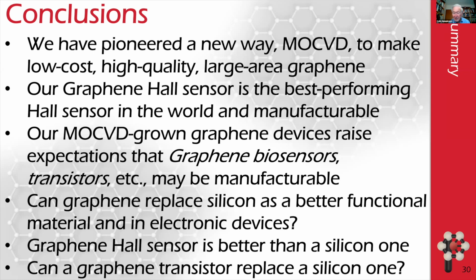It means it changes its sensitivity. And also, quite remarkably, phonons in the substrate affect the mobility of carriers in the graphene. We found out lots of these things, and some of them were known beforehand and sort of not published, but it's really not easy to use. So we've got a graphene transistor, which does work, but not nearly as well as a silicon transistor. And it's a question of improving this and finding out what the limitations are.